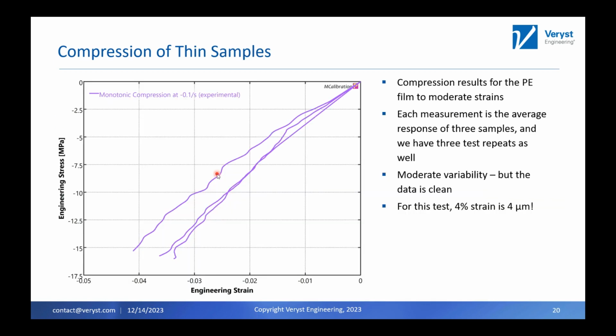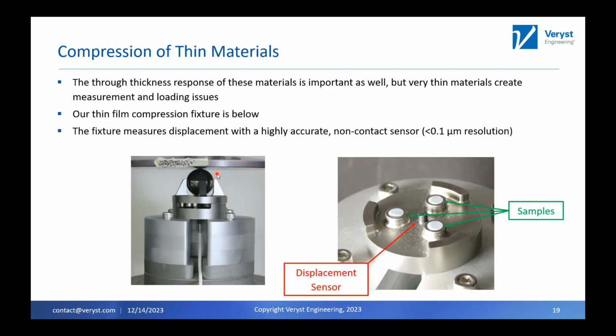So here are the results. It can be tough with these stiffer polyethylene materials to go to very high strain. So in this case, we went to about 4% strain. The other thing you should keep in mind is that essentially each one of these lines is an average of 3 samples because we're loading 3 samples at the same time. Right? We're loading all 3 of these samples at the same time.